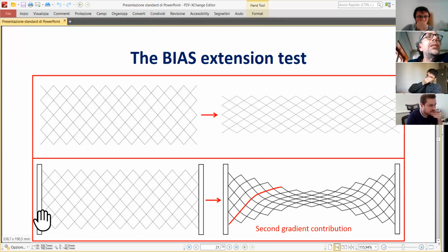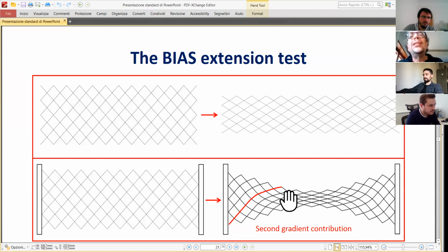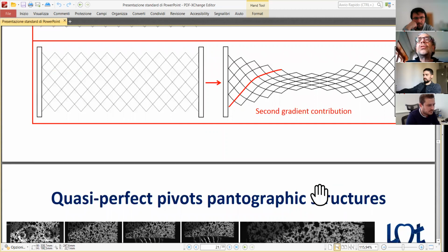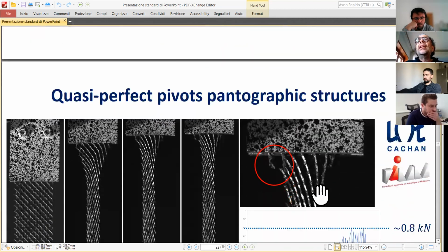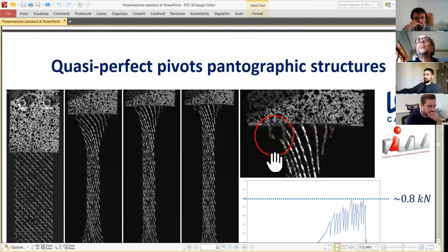If you block the distance between these beams and you elongate, then the bending of the beams becomes dominant in the deformation pattern, and everybody knows that in the deformation of a beam, second derivatives of displacement occur, and at macro level, after homogenization, you get a second gradient continuum. Okay, so this was the idea of the synthesis. Of course, this material is broken.